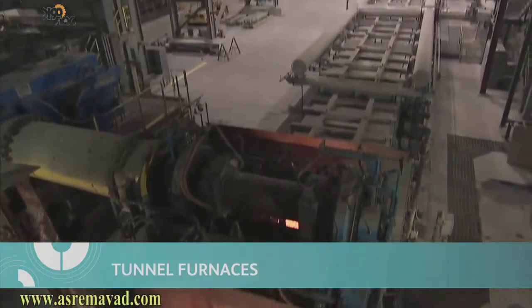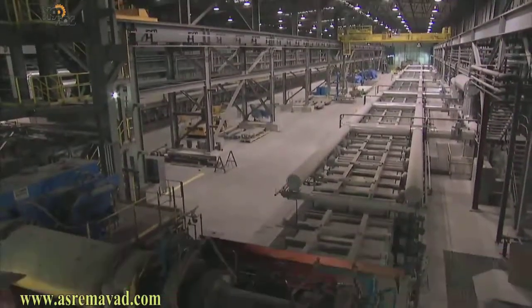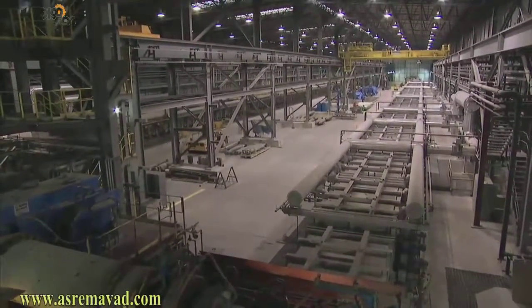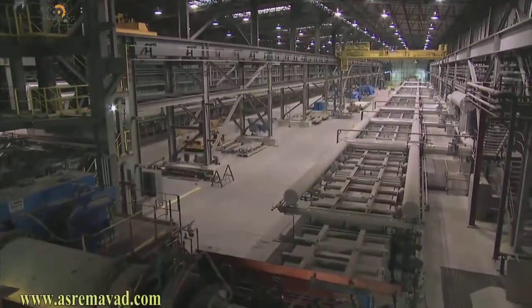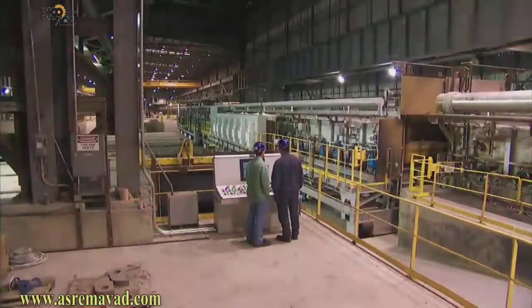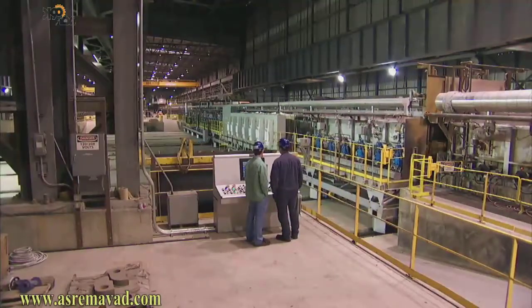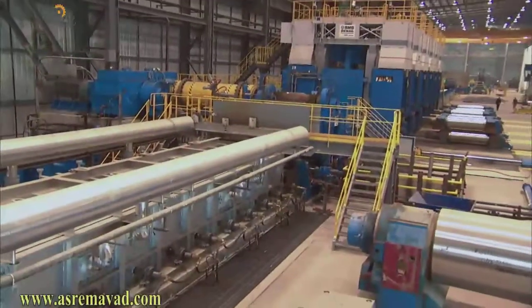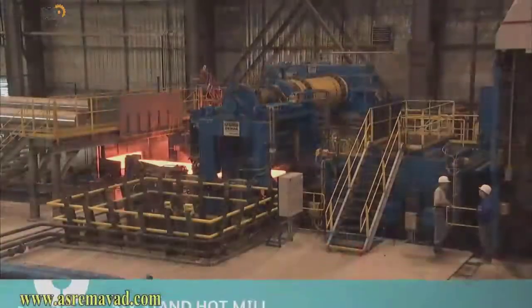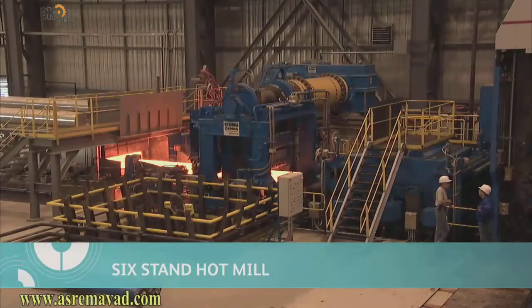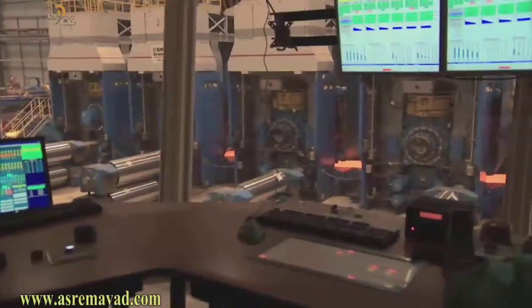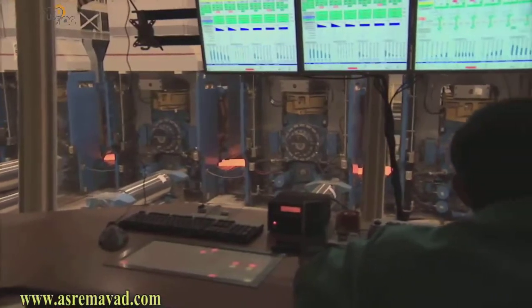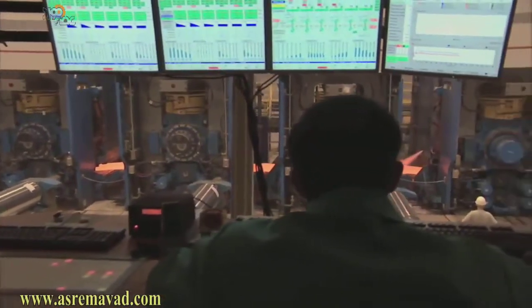The facility houses 2 tunnel furnaces, each nearly the length of 3 football fields, working independently to heat each slab to a consistent hot rolling temperature of around 1,900 degrees Fahrenheit. Leaving the furnace, the slab enters the 6-stand hot mill, where the 2.5-inch slab is reduced as specified by order to thicknesses from 0.054, or about the thickness of a dime, to about 1/2 inch.